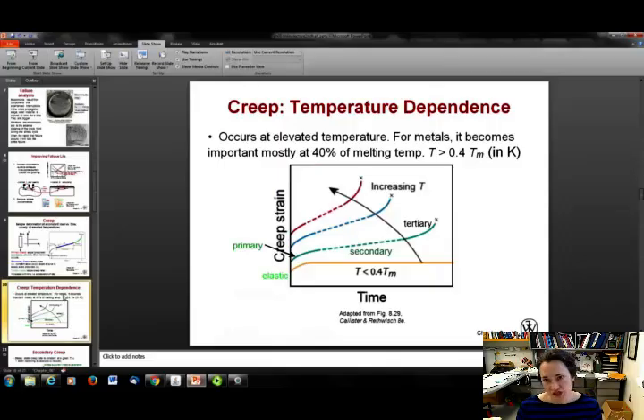Creep, as you can imagine, has a temperature dependence. The hotter your part, the more your creep strain rate will be. The faster the creep will occur. For metals, it becomes important mostly at greater than 40% of the melting temperature. Then it really takes off, okay? So that's something to bear in mind.